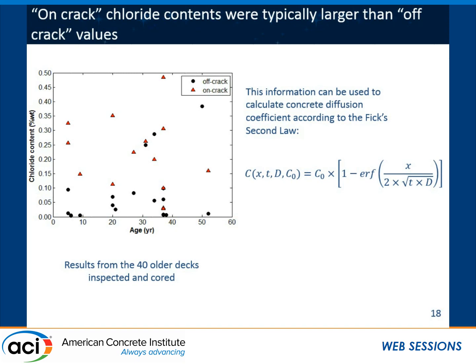Sorry, just one quick question. I really appreciate the presentation. How did you go about measuring chloride at the crack itself? Measuring chloride at the crack itself is essentially you take a core at the crack, and your core is still intact because you have a rebar that transfers across the crack, and then you can drill and pulverize the concrete right at the level of the rebar. So that's how you get it.